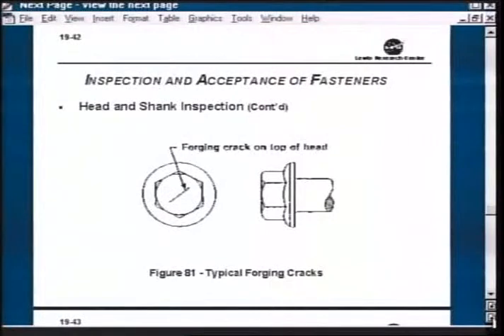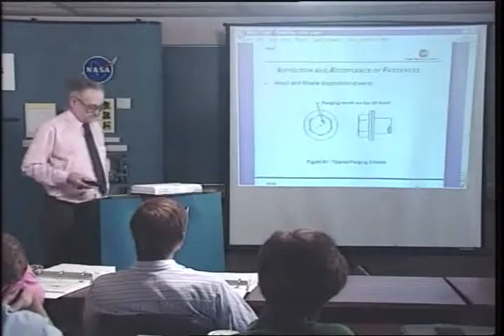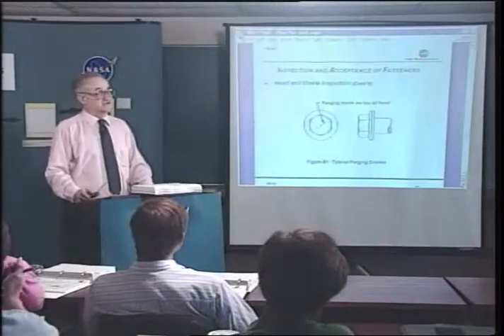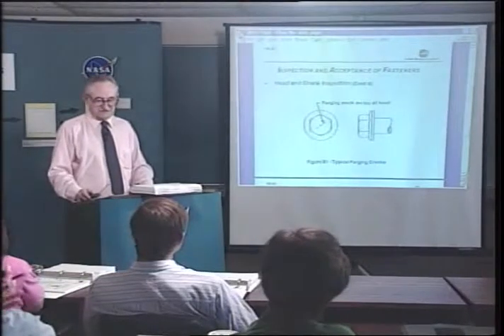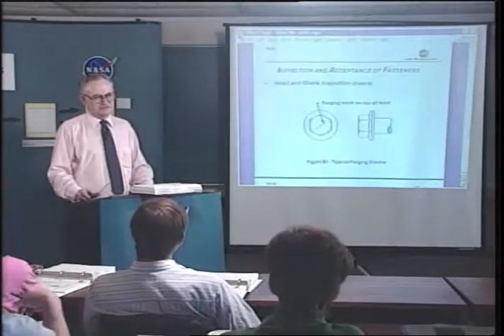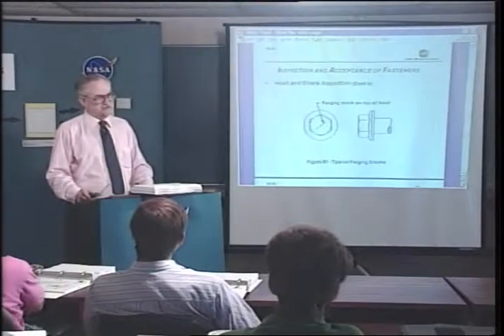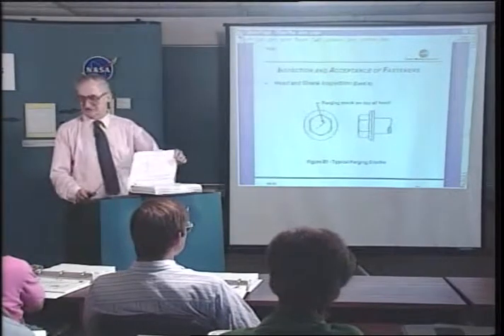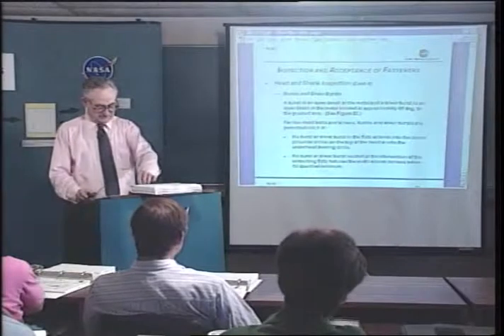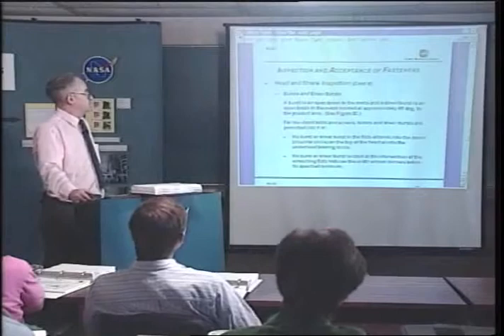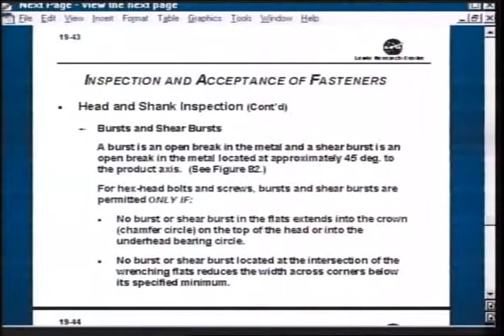Here is one that shows a forging crack on the top of the head. If you look at those limits on depth, you'll see that if you take .04 times the diameter - for a bolt that is say a quarter inch in diameter, that's a pretty shallow crack, nothing more than a streak that you can see. So that type of crack would be acceptable.